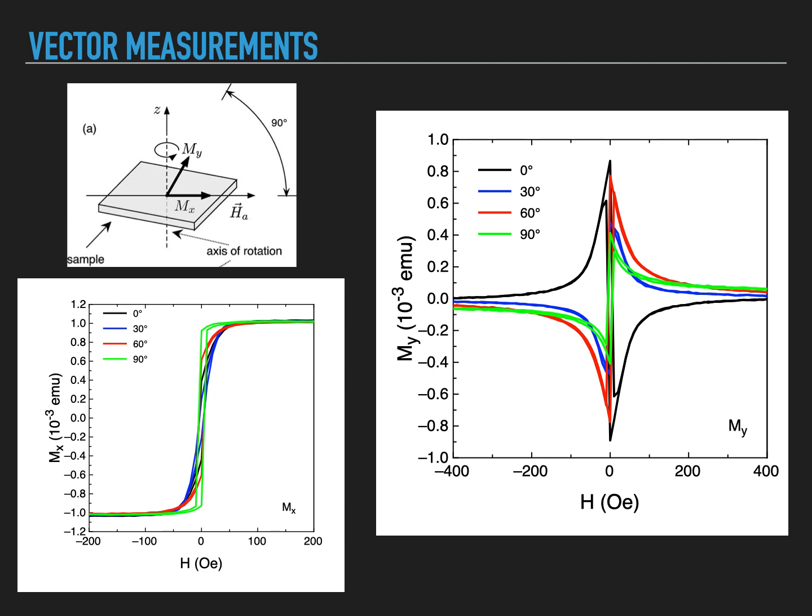Conversely, when you go towards the coercivity, the x component of the magnetic moment will go to zero, and the y component of the magnetic moment can do a lot of different things. Typically, the magnetic moment reorients somehow along a certain direction that is no longer affected by the applied field, and that is the local anisotropy direction, which, if it does not coincide with the applied direction of the magnetic field, means that you have a value of My that is different from 0.